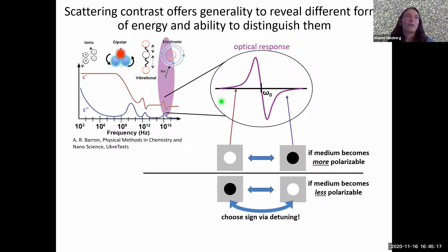If we moved instead and probed on the red side of the resonance, then we would see a pi phase shift. And what's cool is that if the medium becomes less polarizable, then we should see the reverse. So essentially, we have the power to choose what sign of contrast we measure. I showed you basically dark contrast so far, but we can choose that based on the sign of the detuning.